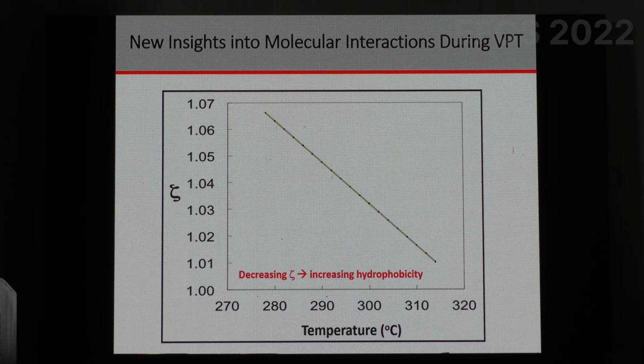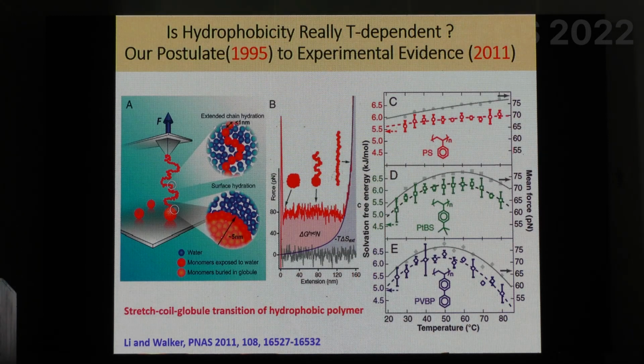The hydrophobicity has to have a temperature dependence, but extremely subtle. It's not a very large change in the hydrophobic parameter. And so for quite some time, when we were publishing these papers, the main question that all the reviewers were asking is: is this true? You're claiming that these hydrophobic interactions should have a subtle temperature dependence, but does that actually happen? And interestingly, there are now these papers which have come out more recently, still about 10 years ago, that actually have done these measurements.